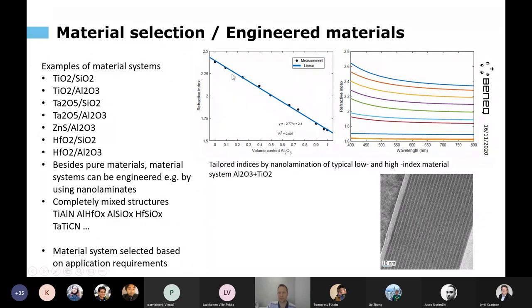So this would be somewhere around here, 20% aluminum oxide content. And optically, this behaves really as bulk material because these are really so thin layers that this is not really an optical stack. This is just bulk material optically. And here are shown the dispersions of these different artificial materials, going from titanium oxide to aluminum oxide, a smooth transition.